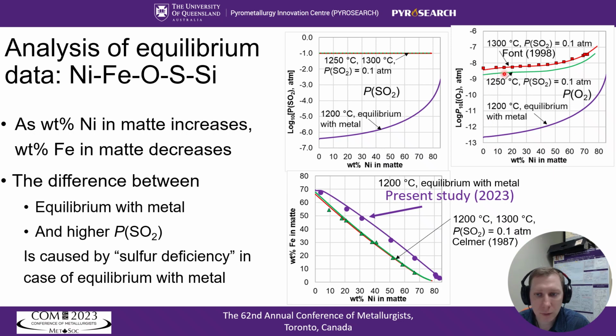We even have experimental data from literature by Font in 1998 to confirm the oxygen partial pressure predictions. So thermodynamically speaking, the removal of iron from matte is achieved by increasing the oxygen partial pressure. So what about the other elements in matte?